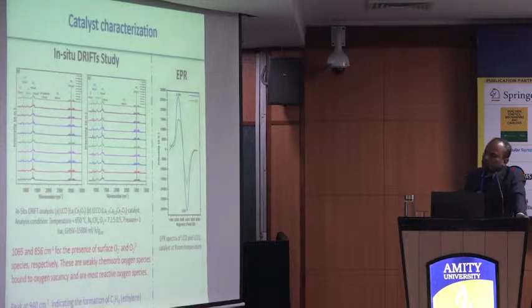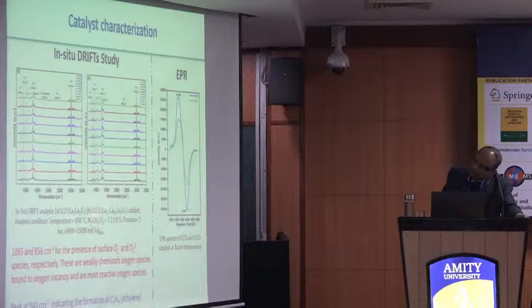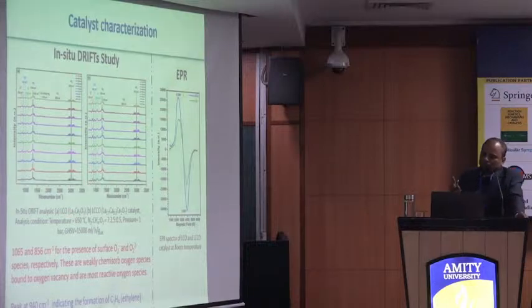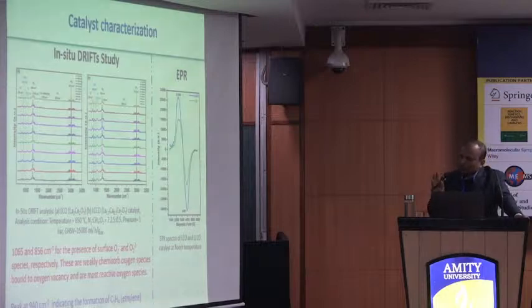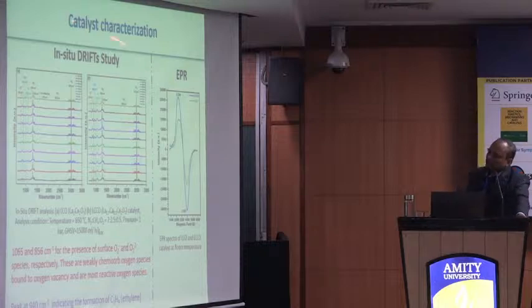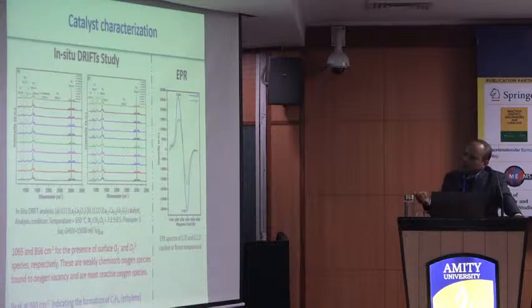We have also done some in situ DRIFT study. Here you can see that there is a peak at 1065 centimeter inverse and also 856, and these two bands confirm the presence of superoxide species O2 minus and O2 2 minus, and these are the active oxygen species doing the activity for this catalyst. We have also done the EPR study, which shows that this superoxide species is present on the catalyst.